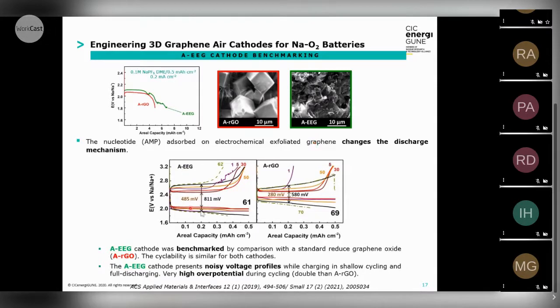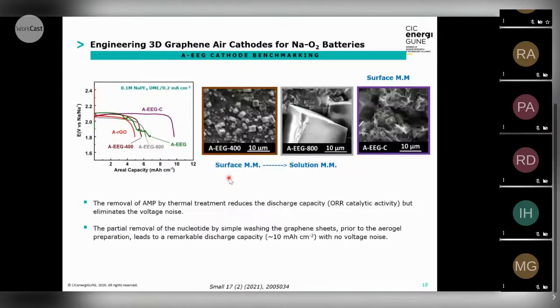But when we went to cycling these batteries, cycling at 0.5 milliamp hour per centimeter squared, we saw that the cyclability was really similar, a bit higher in the case of the RGO, and also that the potential on charge was increasing while cycling in the case of the EEG sample. And also we got some noisy voltage profiles. So we wanted to overcome this and increase the cycling performance.